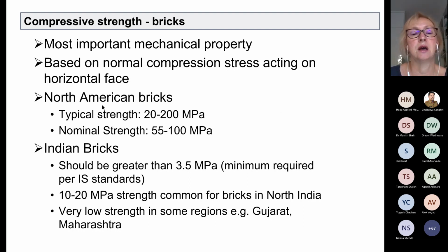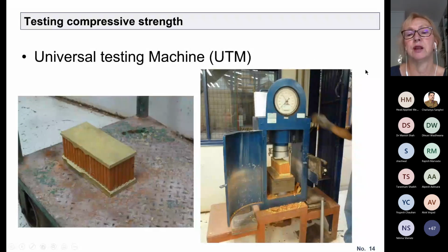In North America, brick strength is from 20 to 200 megapascals, whereas in India, the minimum strength prescribed by IS 1905 is only 3.5 megapascals. So bricks that are 3.5 megapascal strong can be used for construction in India. 10 to 20 megapascal strength is common for bricks in North India, but in Gujarat, Maharashtra, very often you will find bricks that are only minimum strength 3.5 megapascal or even less. Most often, this strength is not even checked. It is specified but not checked by testing, except for larger projects.